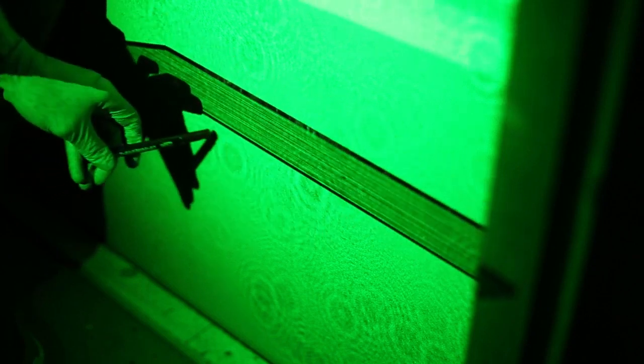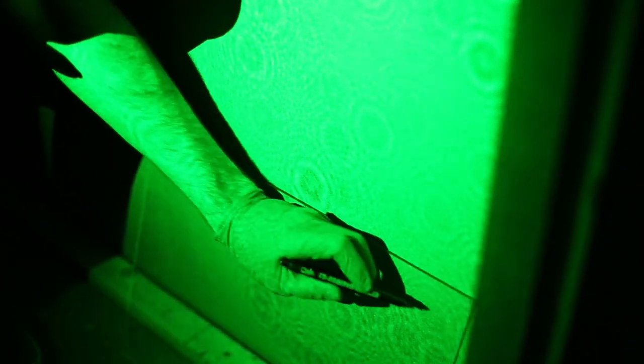You will either see a pattern of parallel lines, or when you turn the glass 90 degrees, you will see a wood grain pattern. To get the optimal hologram, the glass should be oriented so you see the parallel lines pattern. If the correct orientation of the glass is neglected, there will be scatter in the final hologram. With a pen, you can draw an arrow on the glass indicating the direction of the pattern. When you cut the glass a little longer in the vertical size than in the horizontal, you will be able to remember in which direction the lines were running.